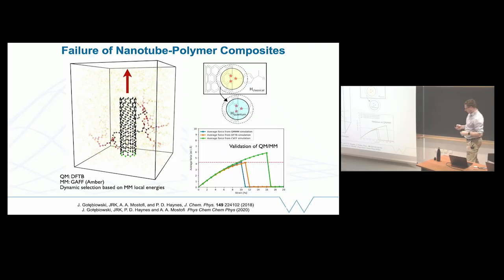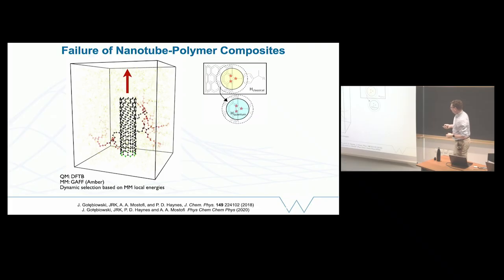This is very local, and so everywhere where there is a point of contact between a polymer molecule and the nanotube, we see a kind of increase in the local energy, the strain energy. So we can actually use the local potential energy as a way of measuring where we are unlikely to trust our classical model, and we can augment locally with lots of little separate spots of quantum mechanical accuracy. This was done using tight binding, so it was a relatively cheap quantum mechanical model. We could place it in lots of places simultaneously.